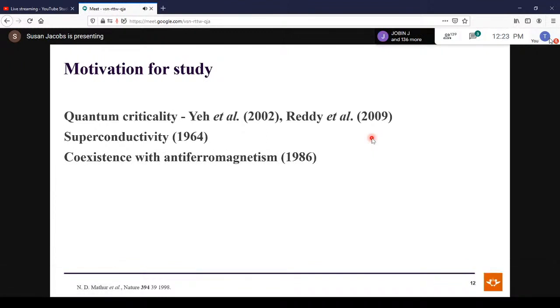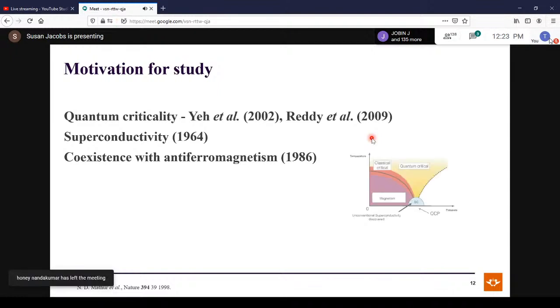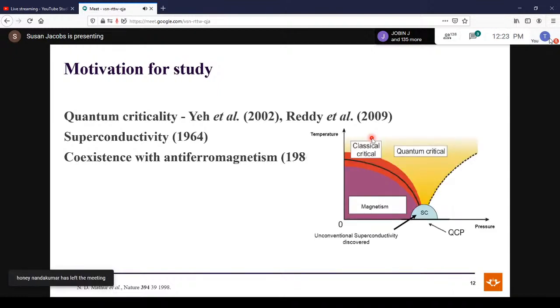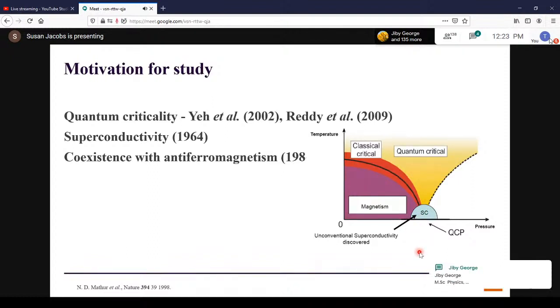So basically, we wanted to see if we can develop a phase diagram like this, where you have the classical critical state going into the quantum critical state at the quantum critical point, and then terminating in a superconducting dome. So this is what we wanted to see if it exists in our system. Here you can see superconductivity coexists with magnetism. So we wanted to see this for the chromium rhenium vanadium alloy system.